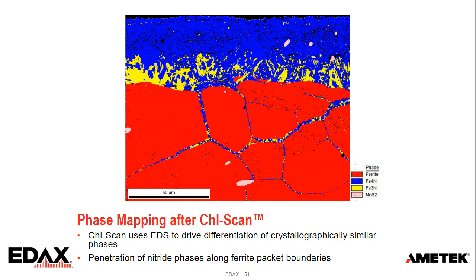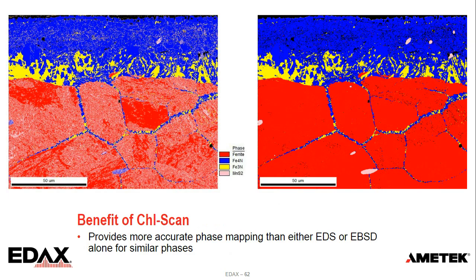And so we can see that in terms of the comparison before and after chi-scan. I think this just shows very nicely why using both together is very nice. It's a very easy way of better resolving the phase information correctly. We get a better overall picture, and there's really no penalty for having both.